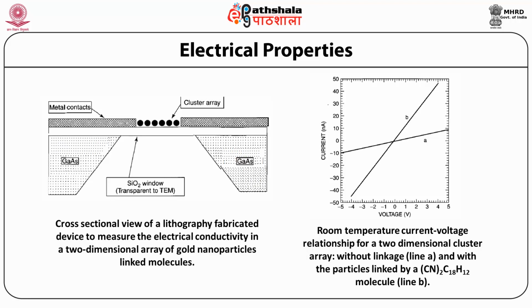These alkyl thiols have an end group SH that can attach to a methyl CH3 and a methylene chain 8 to 12 units long that provides steric repulsion between the chains. The chain-like molecules radiate out from the particle. The encapsulated gold particles are stable in aliphatic solvents such as hexane. However, the addition of a small amount of dithiol to the solution causes the formation of a three-dimensional cluster network that precipitates out of the solution.